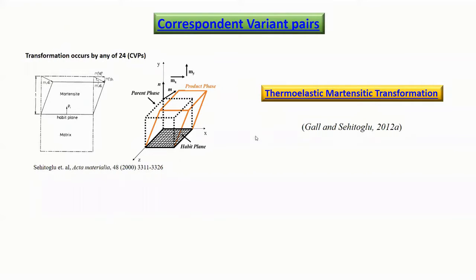So, in the process of this transformation, there is supposed to be a habit plane, a plane which is not going to change its position. Okay, so you can see that this is the parent phase here, the black dotted phase, and this can convert to this orange phase here, but the habit plane will remain the same for both the phases. Okay, so this is very important.